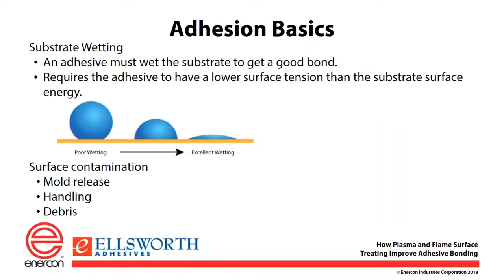What can cause poor wetting? Well, substrates can be part of the problem. You have low surface energy substrates like polyethylene or polypropylene that are very difficult to bond to for many materials. You can also have issues on substrates that aren't as difficult to bond to, such as a mold release agent that might be present on the surface. The panels may have been handled, so you might have skin oils that have been put on the surface of the substrate. You can also have debris or dust on the surface, which will disrupt adhesion as well.